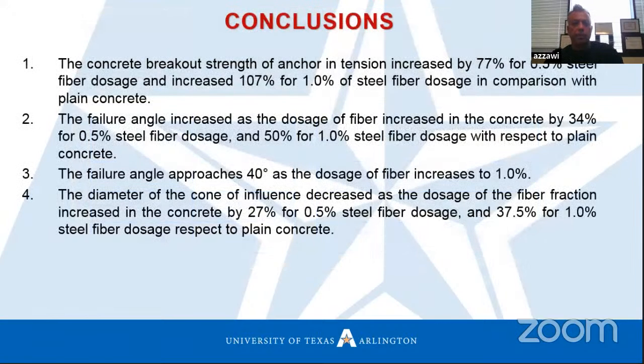This research gives us some conclusions: the concrete breakout strength of anchors in tension increased by 77% for 0.5% steel fiber dosage, and by 107% for 1% steel fiber dosage, in comparison with the plain concrete. Also, the failure angle increased with increasing dosage of fiber. The failure angle approaches 40 degrees as the dosage of fiber increases to 1%. The diameter of the cone of influence also decreased as the dosage of fiber increased.